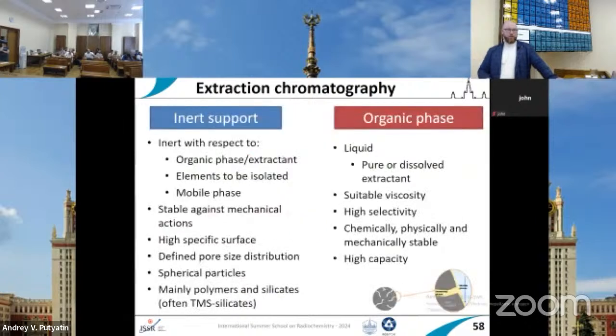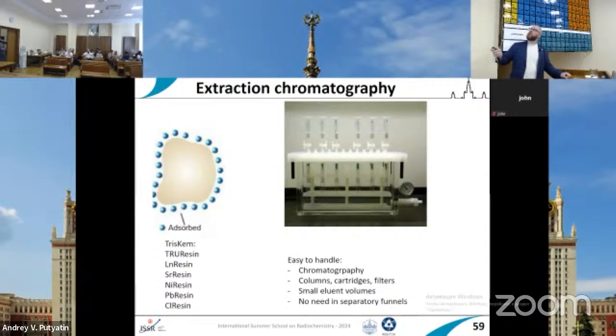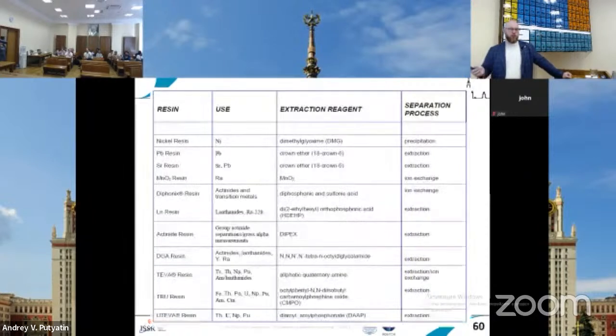absolutely the same molecules. So normally we have some inert, porous support, where you place your extractant, your selective molecule, with the diluent, and then you evaporate the diluent, and there is a pure extractant molecule in the pores. You make columns like these, small cartridges with your resin covered with the extractant molecule, and you pass the aqueous solution through this small cartridge and separate your radionuclides. There is an example of commercially available resins that are used for certain radionuclides. So if you know which radionuclides you would like to separate, you can just use this table and use the appropriate resin.